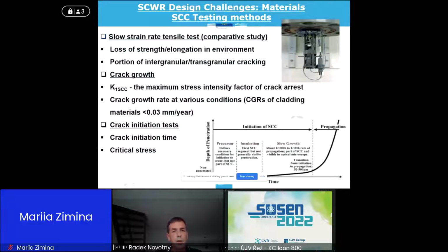If we look at what we are getting from this type of test, I would like the crack growth rate, which will help us to define what the stress effect on SCC is. What is the maximum stress intensity factor for crack arrest? And then of course we can create so-called disposition lines. That means the dependency of crack growth rate on stress and on all various conditions in the core, even related to chemistry or materials.